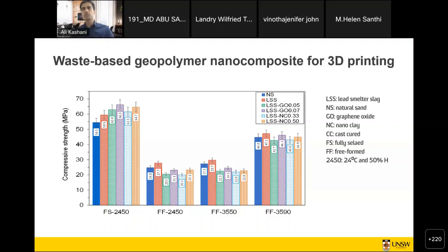And again, we put it in similar conditions. One condition is properly cured; in another condition, we take the samples out of the mold after 4.5 hours and put them in different environmental conditions, to better represent the free-form condition of 3D printing. If you look at the left, that is just the standard condition of curing.